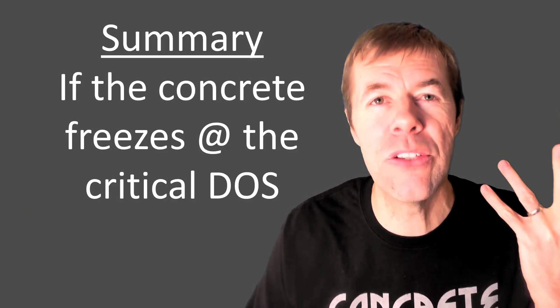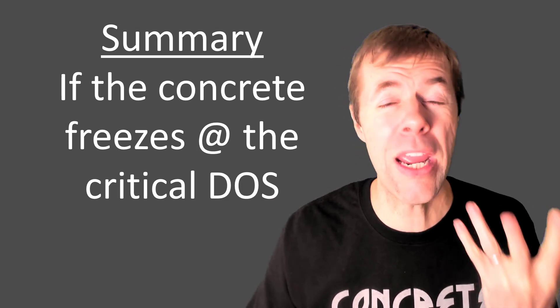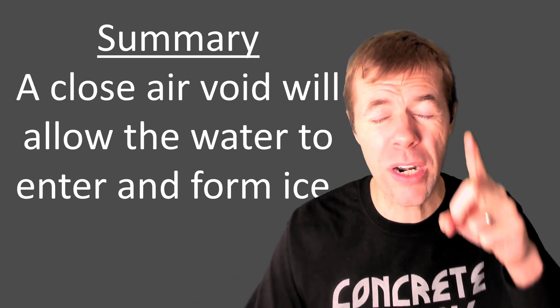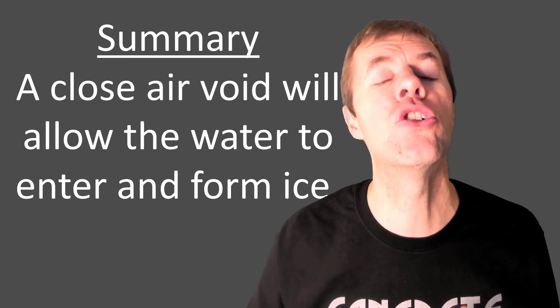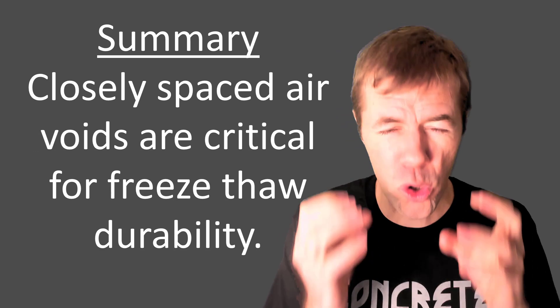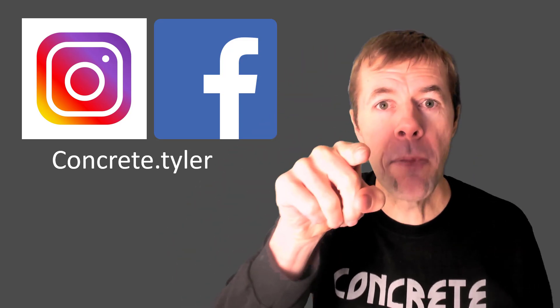In summary: if concrete freezes at the critical degree of saturation or higher, ice forms in the capillary pores causing increased pressures, which shoves water into an air void to relax the pressure and keep it in equilibrium. Closely spaced air voids are critical for the freeze-thaw durability of concrete, and you can keep concrete safe by keeping the degree of saturation low. If you enjoyed this video, please give me a thumbs up and subscribe. And if you're wondering what happens if there are salts involved, I've got a video all about salt scaling. Take care, everybody. Peace.